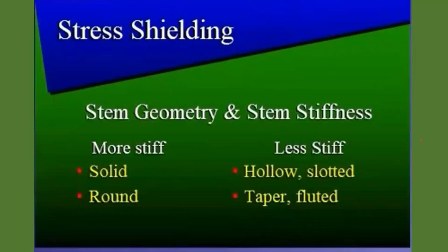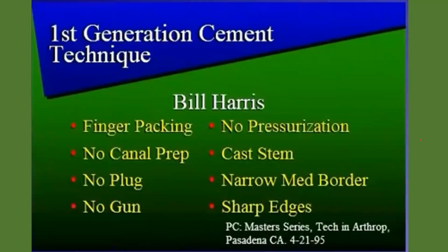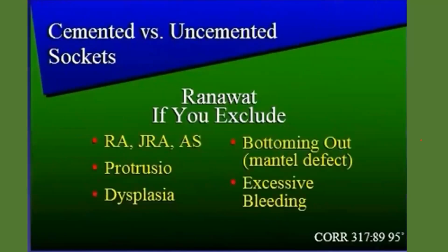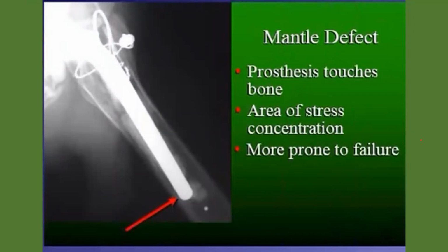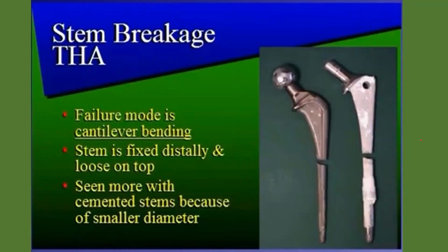I want to mention something also. I have been talking very long and I can hardly talk, but I want to mention, if you get a stem like this, don't show it to your friends. This is a very bad stem. You have to aim at centralizing your prosthesis, because this will create a zone of stress. Distal fixation, distal pores, you'll create a cantilever effect and you can get breakage of the stem.